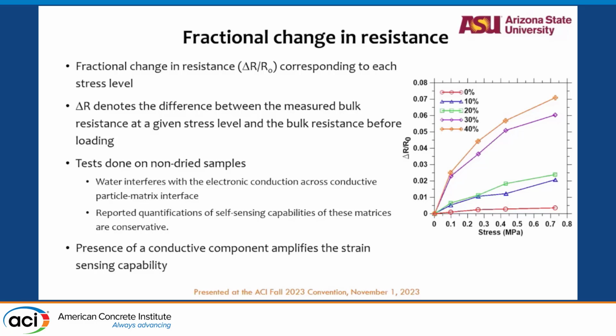For the fractional change in resistance, we compared the stress state with delta R by R naught. R naught is the initial resistance of the mix when there is no stress applied onto it, and delta R is the difference that we see from the initial state to the stress state. You can see that when there is no iron powder incorporated into the mix, the change is very low, even with higher stress. As the percentage of iron powder increases, the differences keep on increasing and they are quite significant. And this again is a tensile stress that we are plotting this against.